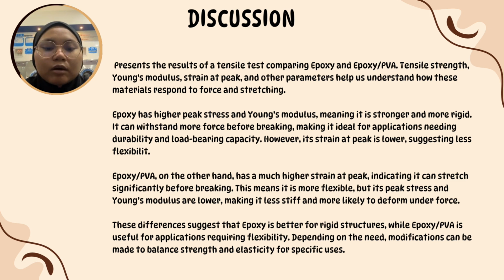Epoxy plus PVA, on the other hand, has a much higher strain at peak, indicating it can stretch significantly before breaking. It means it is more flexible, but its peak strength and Young modulus are lower, making it less stiff and more likely to deform under force. This difference suggests that epoxy is better for rigid structures, while epoxy plus PVA is useful for applications requiring flexibility. Depending on the need, modifications can be made to balance strength and elasticity for specific use.